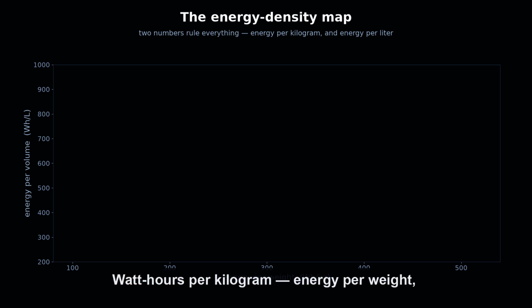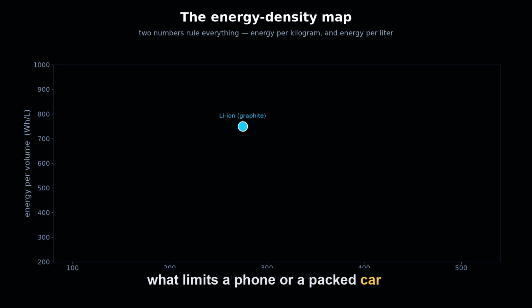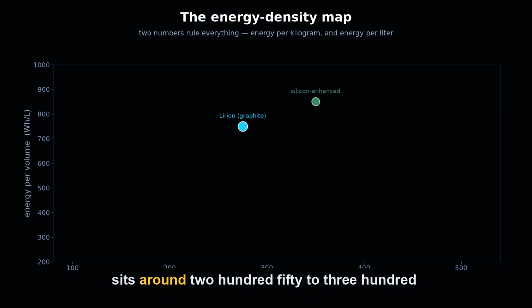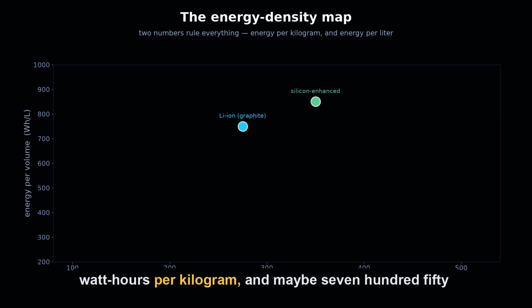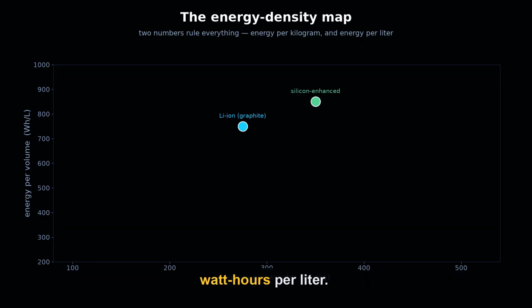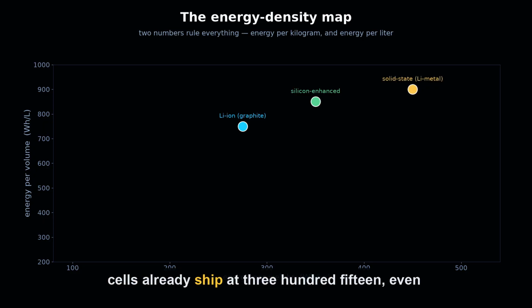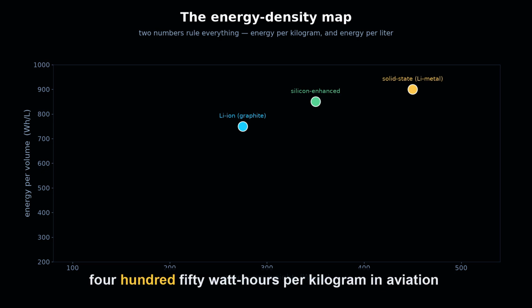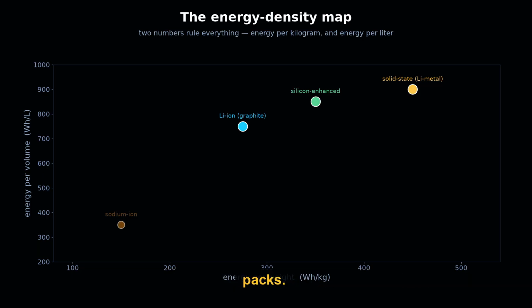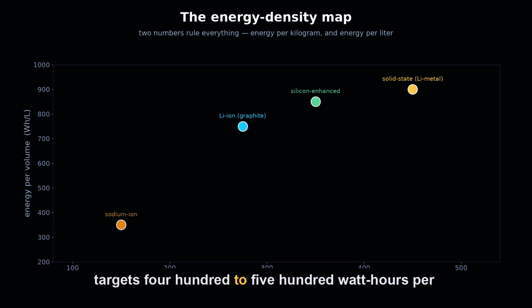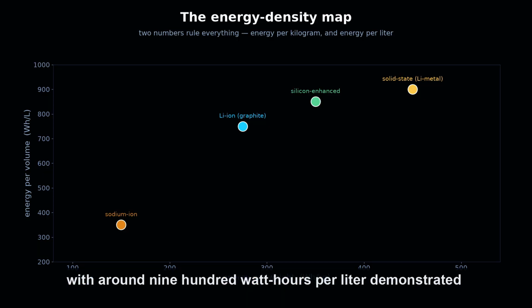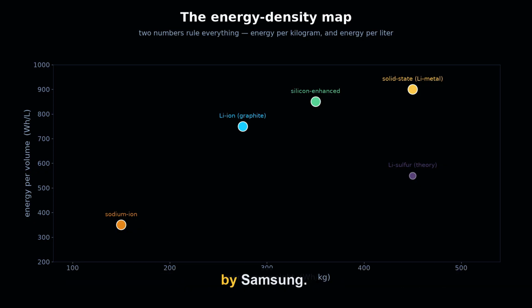2 numbers matter: watt-hours per kilogram, energy per weight, what limits an airplane or a drone, and watt-hours per liter, energy per volume, what limits a phone or a packed car floor. Today's lithium-ion sits around 250 to 300 watt-hours per kilogram, and maybe 750 watt-hours per liter. The prizes ahead push both. Silicon-rich cells already ship at 315, even 450 watt-hours per kilogram in aviation packs. Solid-state targets 400 to 500 watt-hours per kilogram, with around 900 watt-hours per liter demonstrated by Samsung.